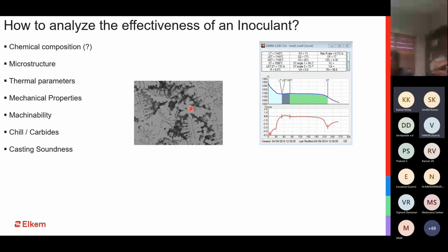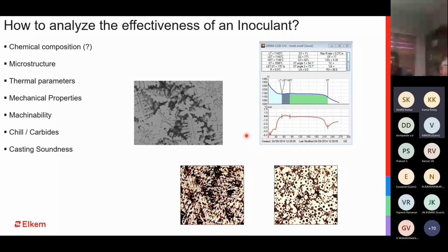How do you control this? You control this by having a more uniform solidification, by creating more nucleating sites, by making sure that you have a very good inoculating effect in the system, and also by controlling the rate of solidification. And if you are not able to control the rate of solidification in the given time of solidification, you have to control the rate of graphitization. So you ensure enough graphite, you ensure that you do not have this directional solidification, you ensure that you have enough graphite precipitation, which would compensate for the volumetric shrinkage, and thereby you get much better casting soundness and do not end up with something like this. Or something like this, where you see these carbides and where you see this not-so-good nodularity.